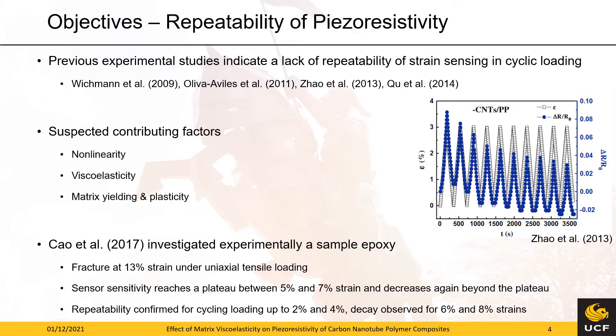In fact, Cao and his colleagues could show that a carbon nanotube epoxy composite exhibits linear behavior up to a plateau in the relative resistance change between 5 and 7 percent. This plateau was followed by a decay of the relative resistance change beyond the plateau and up to the failure strain of 13 percent. The follow-up cyclic studies showed perfectly repeatable behavior for an upper strain level of 2 and 4 percent respectively. However, the cyclic tests achieving upper strain levels of 6 and 8 percent exhibited the decay of the sensor sensitivity with each cycle.